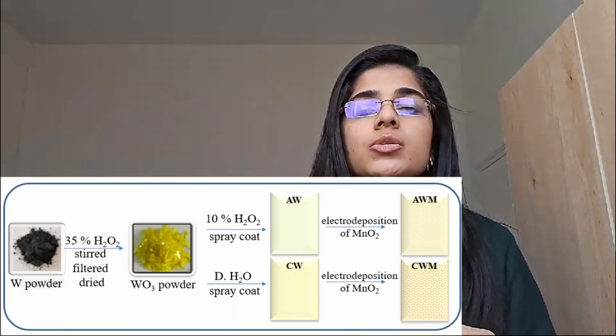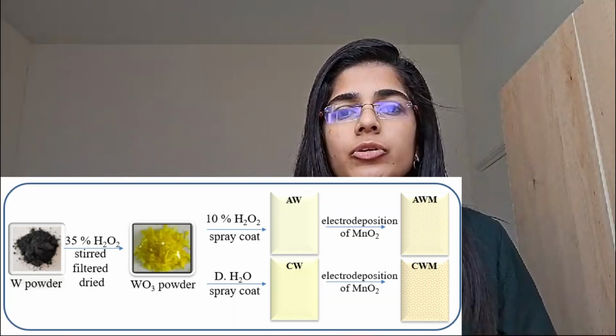MnO2 possesses practical advantages due to its exceptional electrochemical stability and wide potential range. The electrochromic and storage performance of both amorphous and crystalline phases of the WO3, which were coated with MnO2, were investigated using a trivalent aluminum ion containing gel electrolyte. The MnO2/WO3 bilayer was created using a mix of sol-gel and electrochemical methods.